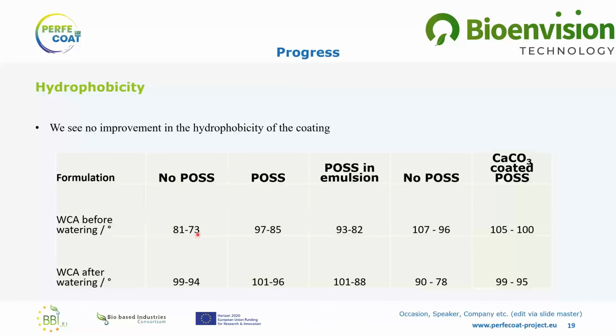And you can see that the effect of POSS is not great compared to the coating without POSS. And we can also see that the hydrophobicity decreases with time, and the time used here is 180 seconds. And the same can be said after the coating was immersed in water for 24 hours.